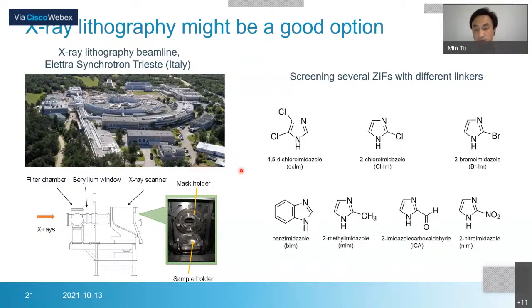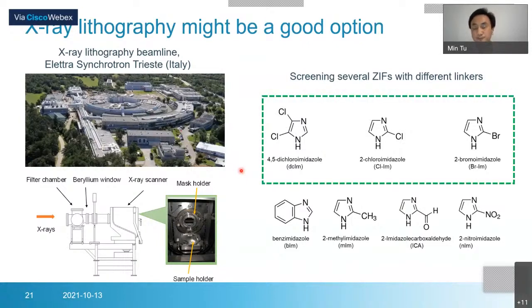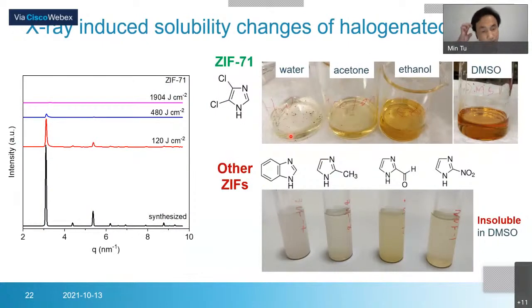Then we can introduce some chemical, some solubility changes. So we found one of the typical types of MOFs very interesting: these halogenated MOFs. Taking one example, again, dichloroimidazole, we found very interesting properties. When we irradiate this kind of MOF with X-ray, we first see the loss of the crystallinity. So with irradiation, we see the loss of the crystallinity.